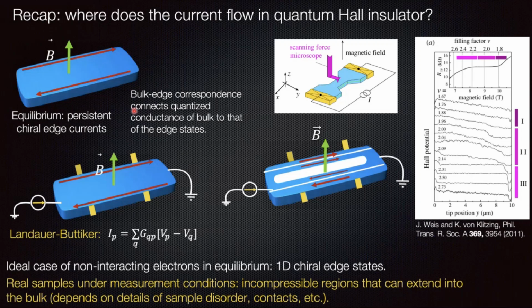So depending on whether you're at thermal equilibrium or away from equilibrium, under what conditions of bias you're operating your device and so on, you do get flow into the bulk states of the sample, because there are incompressible regions that carry this dissipation-less current, and the incompressible regions can extend into the bulk of your sample depending on the conditions. And these are conditions that depend on the details of the sample. But nonetheless, you still preserve precise quantization. And this is at a fundamental level because I think of bulk edge correspondence.